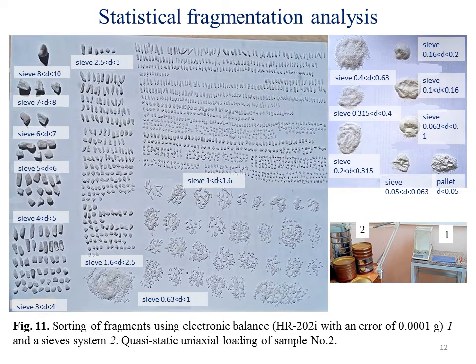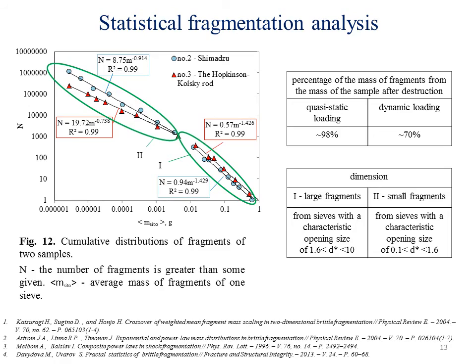Sample fragments were sieved across a sieve system and weighed. The total number of fragments was counted on each sieve. On any sieve under consideration, there were fragments the shape and size of which are characterized by similarity. The weight of the fragments was 98% of the initial sample mass.